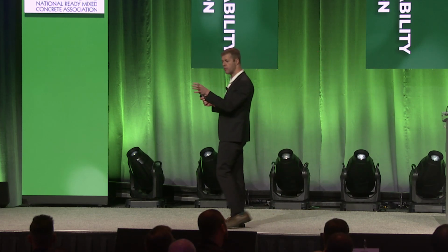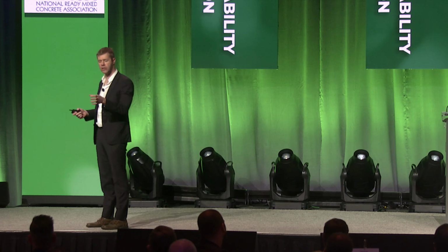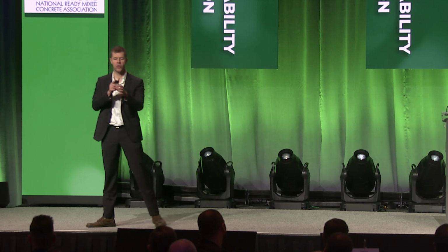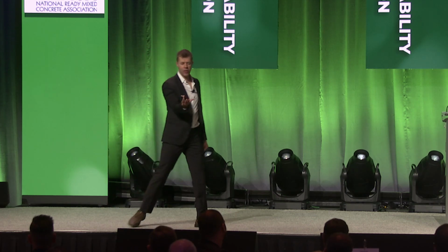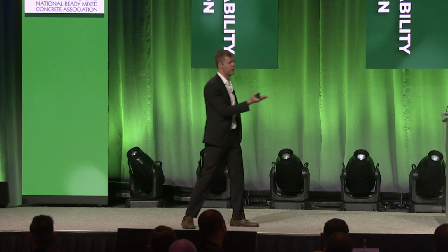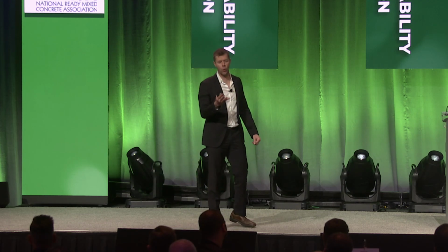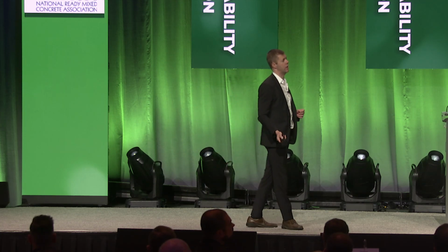Now, one thing I left out is that when you go to actually start the test, you weigh the cylinder empty, and then you weigh it full of concrete, and then you weigh it after you dump it out. Why do you do that? You've got to make sure they dumped all the concrete out. You weigh the pan empty, you weigh it full, and you put it in the oven, you cook it, and you weigh it again until you measure and you've released the water out of that mix, okay?